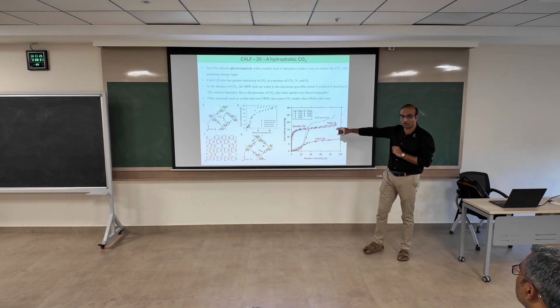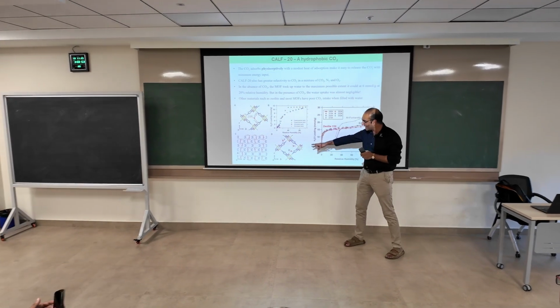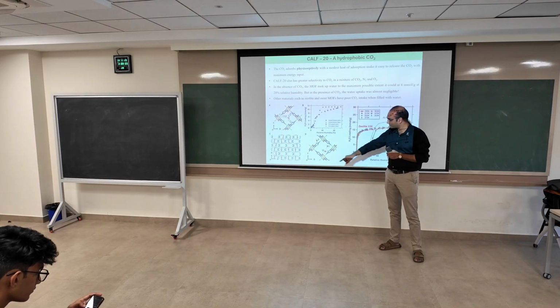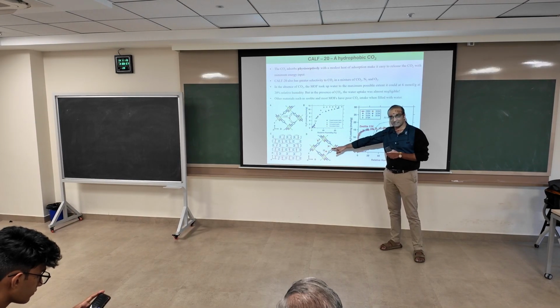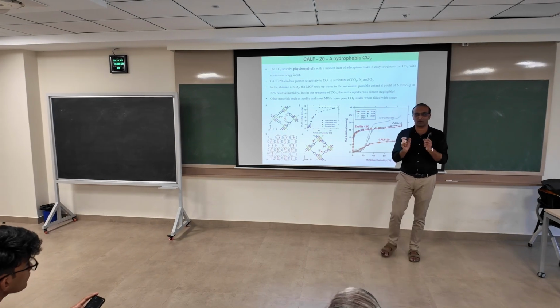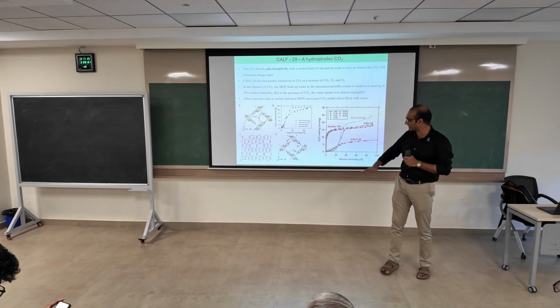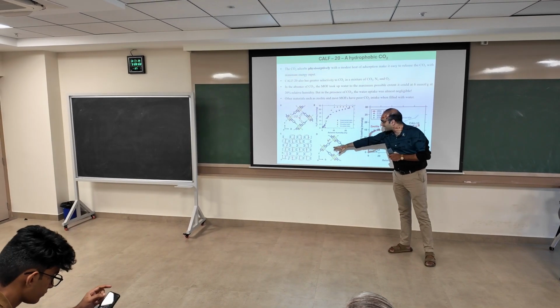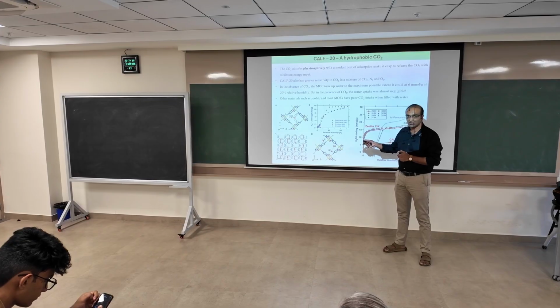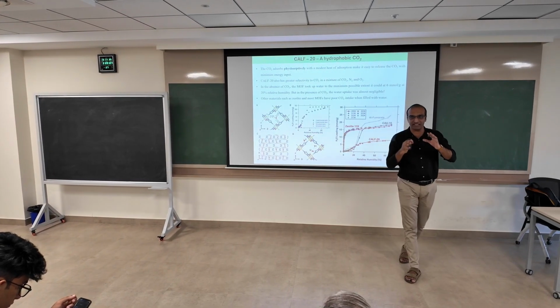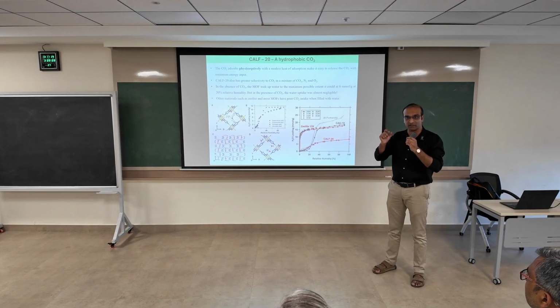It is slightly hydrophobic. Okay, what was happening was the way it was designed, in each pore, water could only adsorb on certain facets, and it couldn't form hydrogen bonding that much extensively inside the pore, and the CO2 would be exactly at the center. Okay, it is a very weak linkage, a very weak van der Waals interaction where it is not bound strongly.